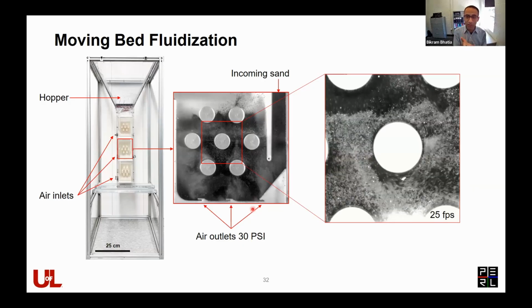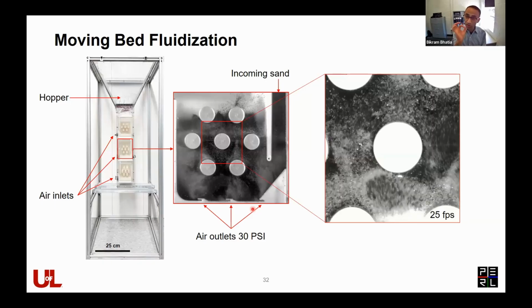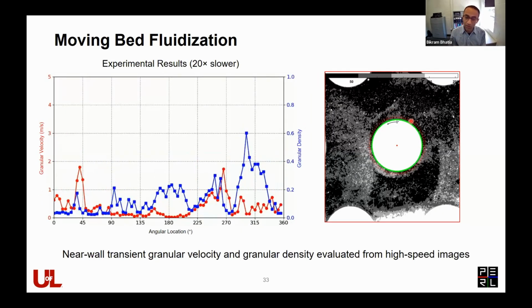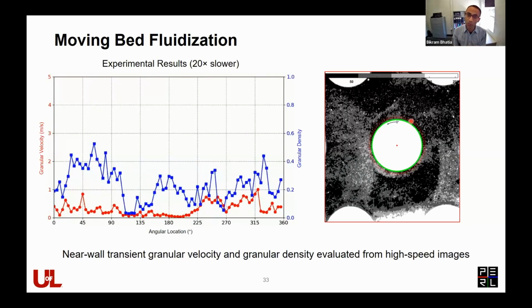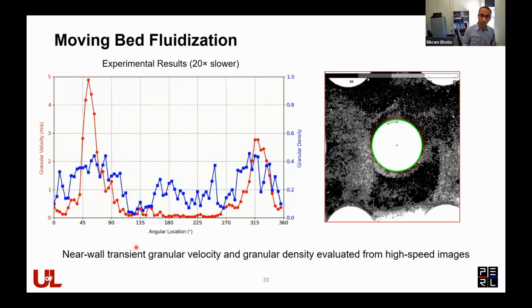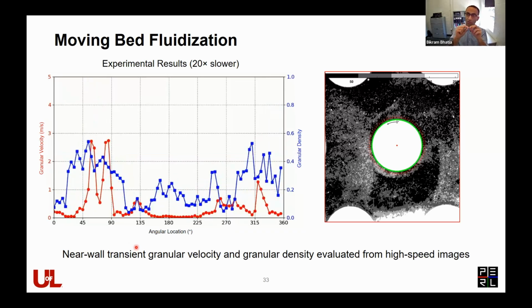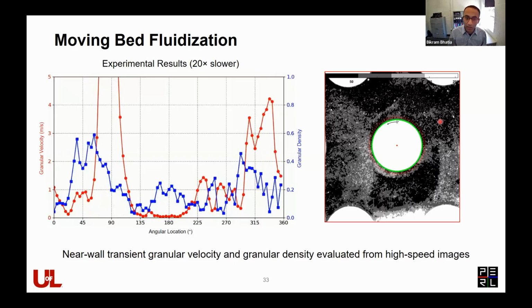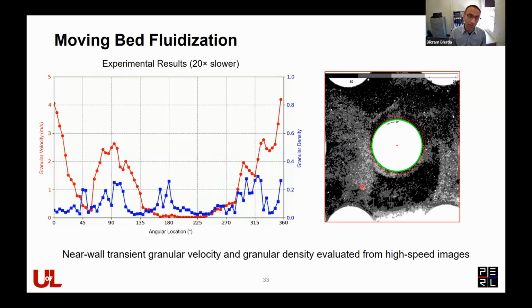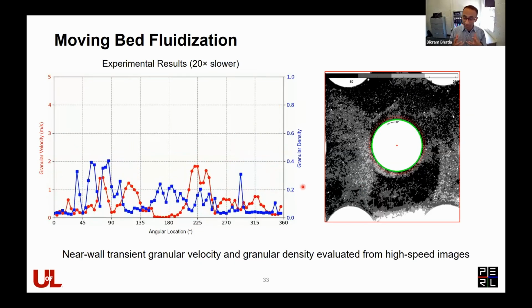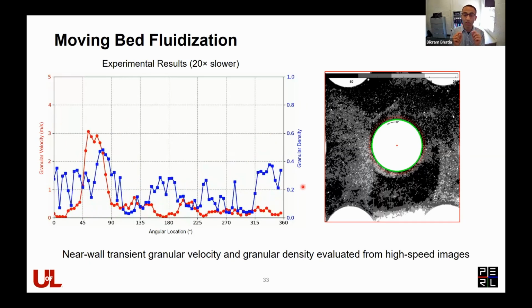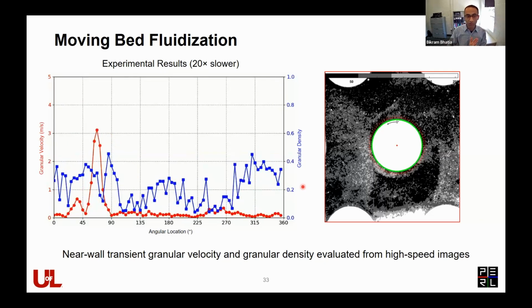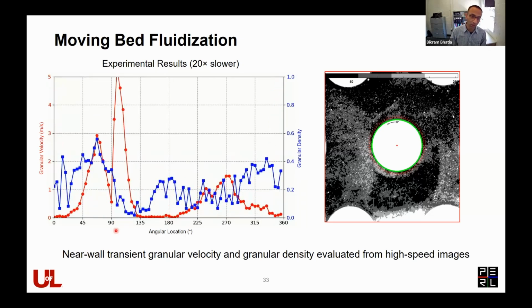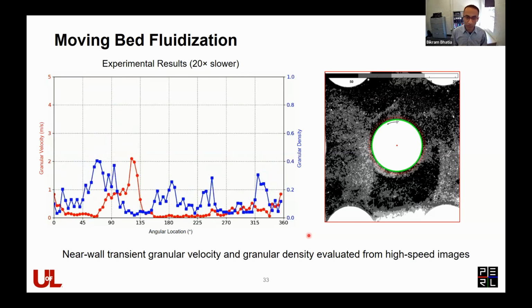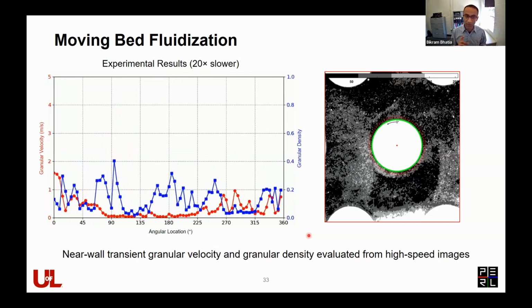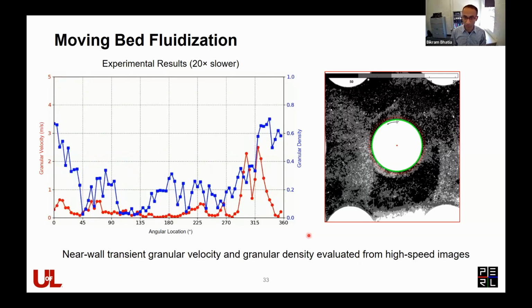So like before, we did high-speed imaging and focused only on the near wall region, basically around 10 particle radii around the tube wall. And we calculated what is known as a granular velocity. This is essentially the velocity of the particles in this near wall region as a function of the angular location of the particle. And we evaluated what the density of these sand particles is in that particular region in our experiment. It is obviously a function of time, which is what you see in the video that's playing on the left, as a function of angular location. It fluctuates quite a lot, and so our challenge was to understand how this correlates with the heat transfer to this tube wall.